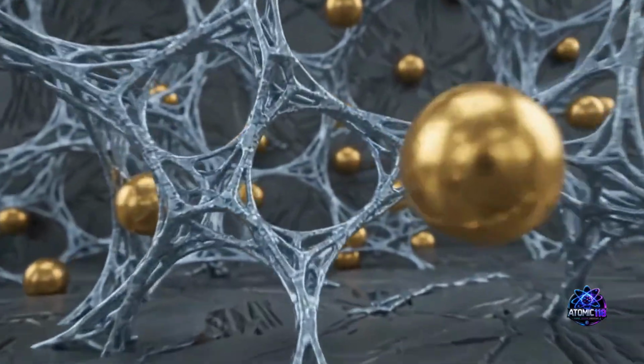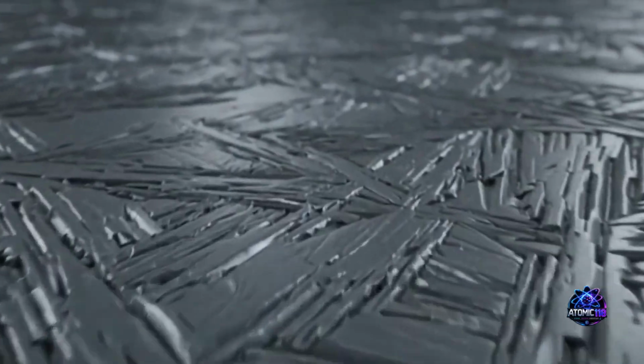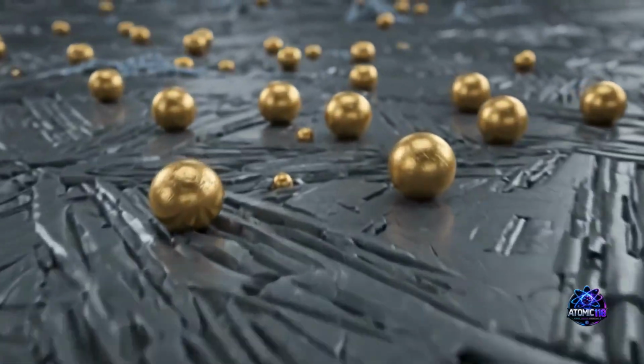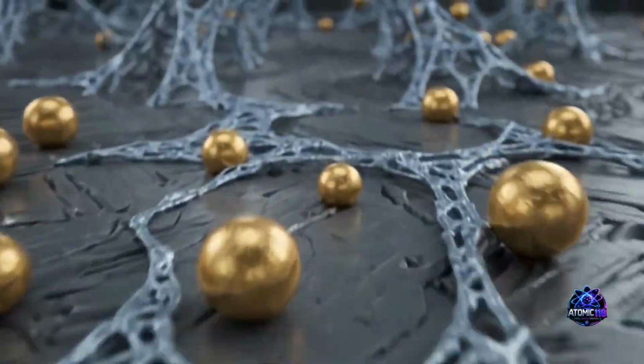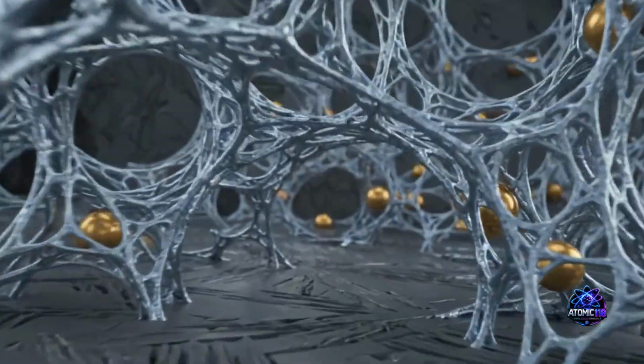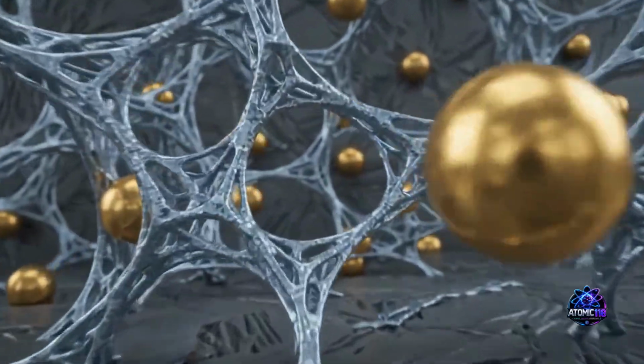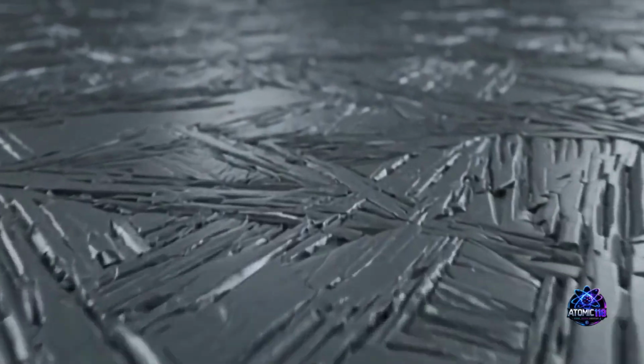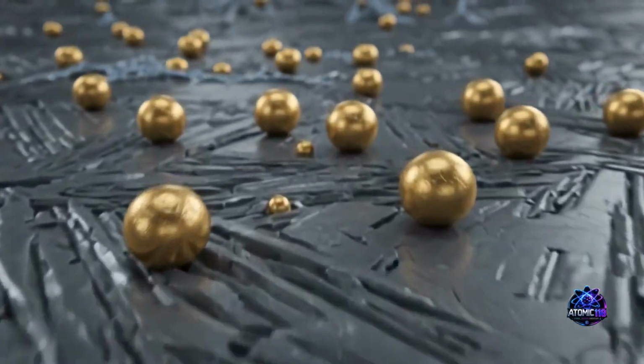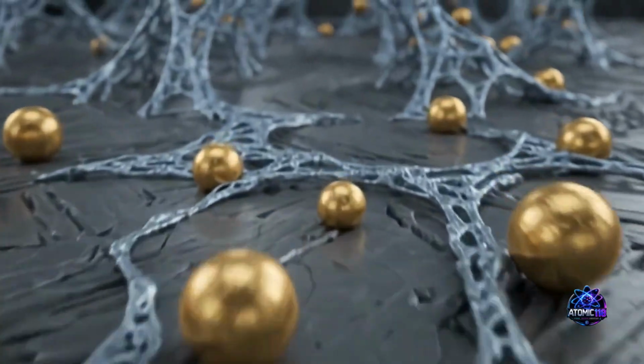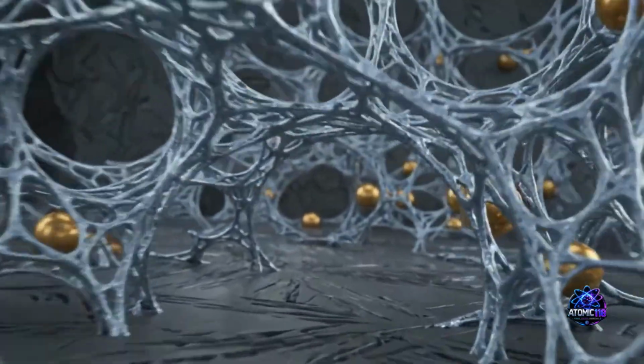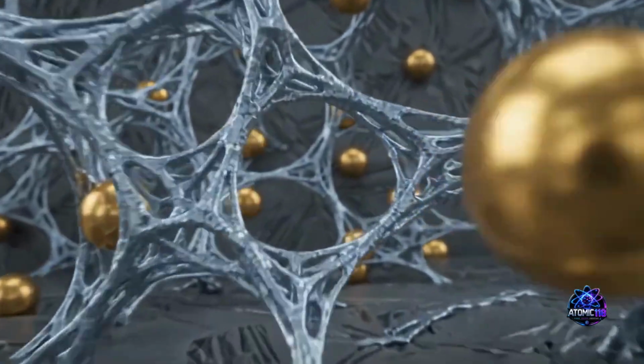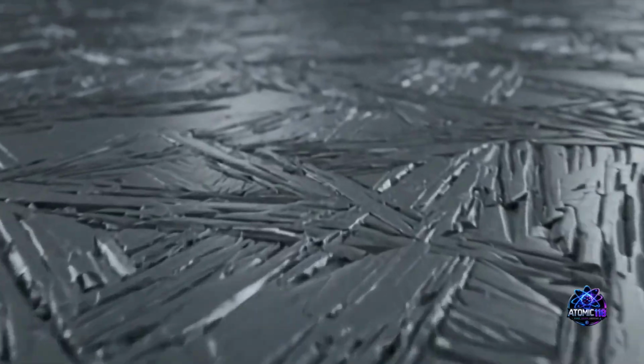Mill rolls. These are massive steel cylinders used to crush and flatten glowing hot metal in steel mills, right? Yes. They endure nightmarish friction, blistering heat, and crushing physical pressure all at once. Literally the ultimate torture test. And historically, the sources show engineers relied on tungsten to harden these rolls. But tungsten introduced a fatal flaw during centrifugal casting.